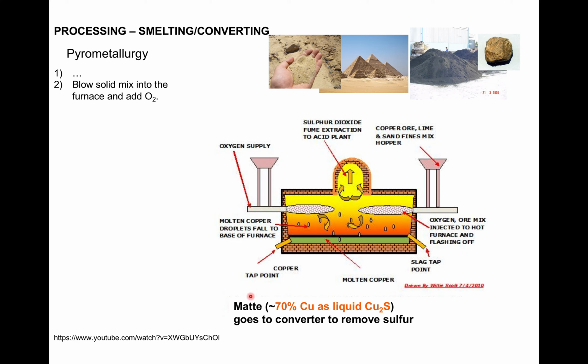to as matte, and matte has a composition Cu2S, so two atoms of copper and one atom of sulfur. And that matte is what we tap coming out, in this case, on the left side of the furnace. And it's coming out of the bottom. So it's shown here at the bottom of the smelter in green.